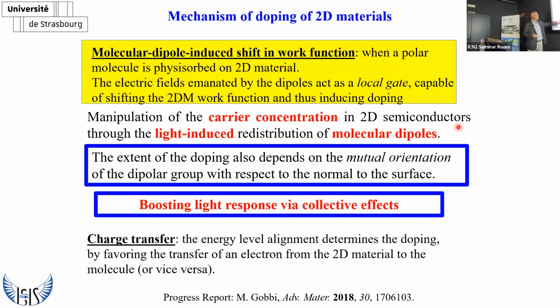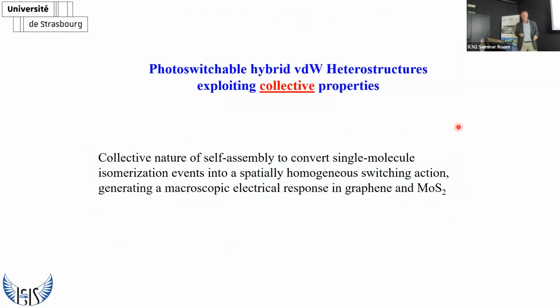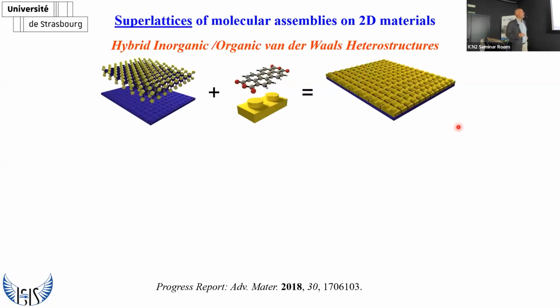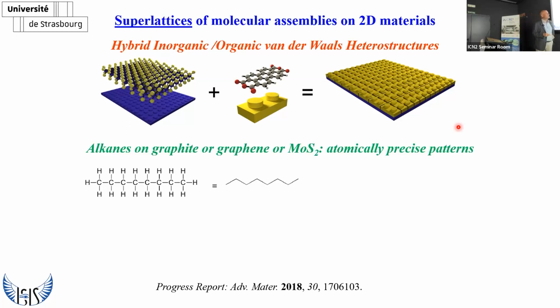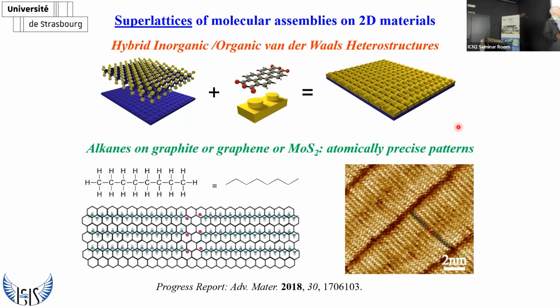So to make the long story short, if you want to boost this effect, you need to try to exploit collective effects. The second one is based on charge transfer, which I will show you in a minute. So collectivity is something that you can achieve by self-assembly, something that allows you to have a high doping effect. And then if you play with responsive molecules, this is something that you can actually turn on and off, the doping effect. So in other words, what we do is to grow a superlattice of molecules on top of the 2D materials. So you play with Lego, and the way to play with Lego is very simple, because both graphite, which has the same basal plane of graphene, and MoS2 love very simple molecules, the simplest molecules ever, that are long alkanes. And this is proven by the fact that, for example, they create a lamellar structure that has been visualized by scanning tunneling microscopy here.